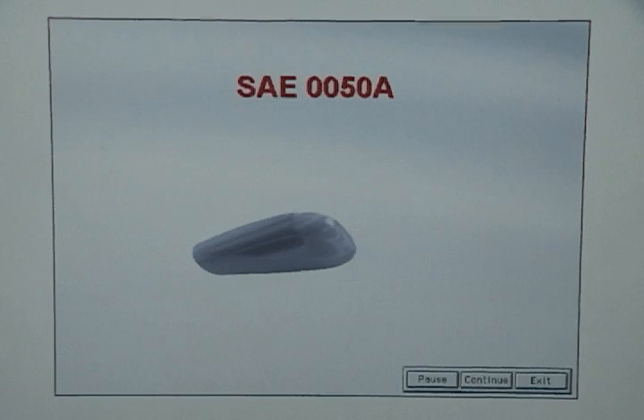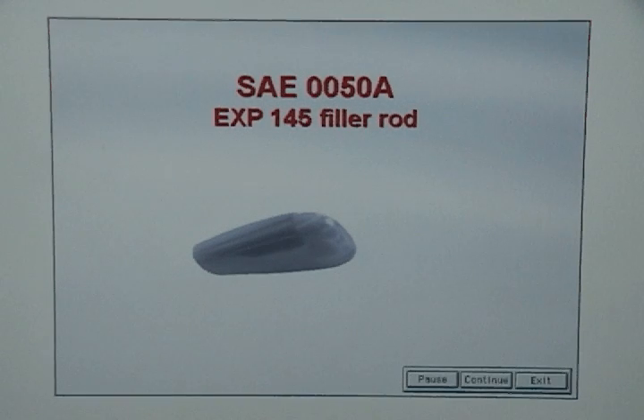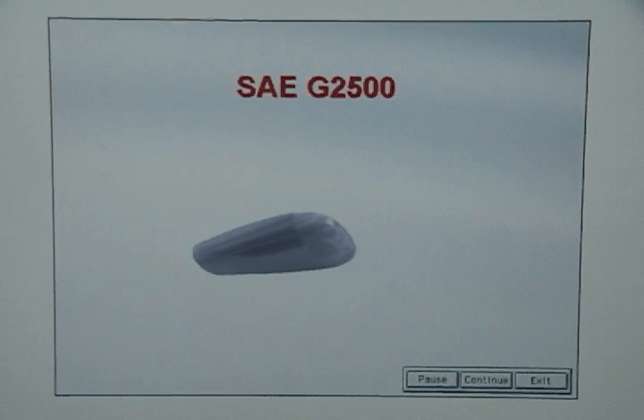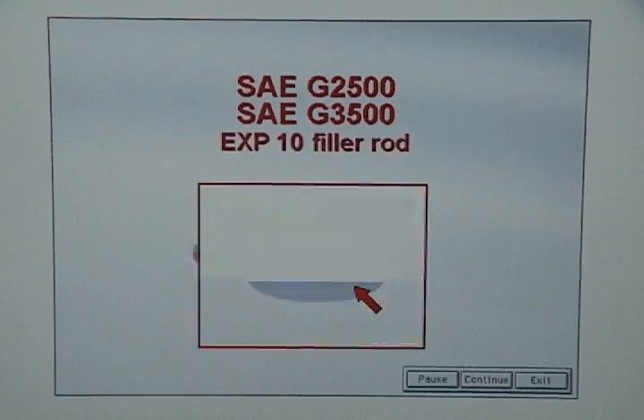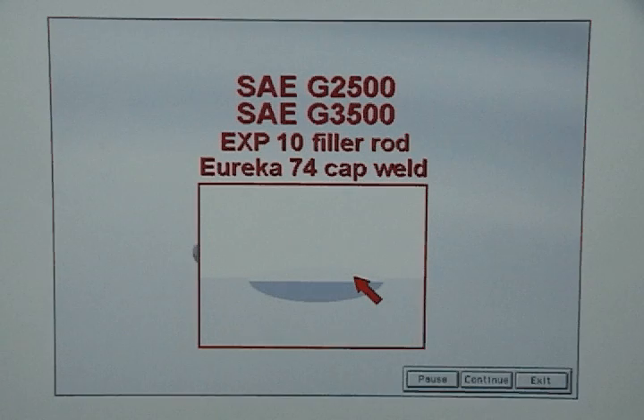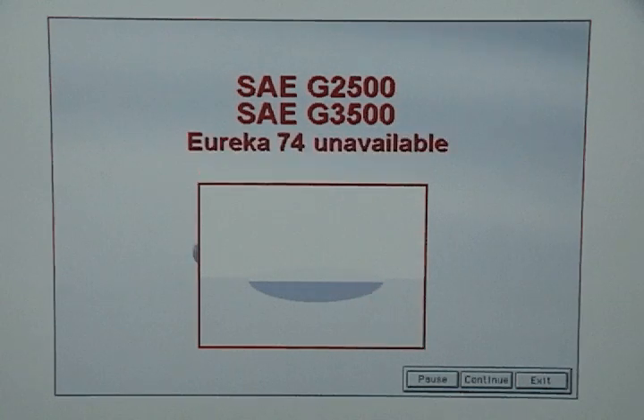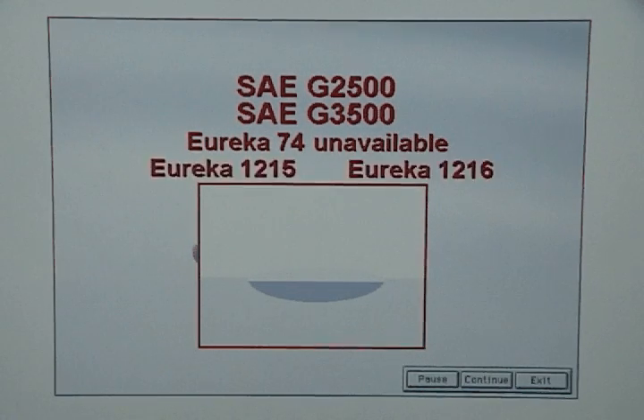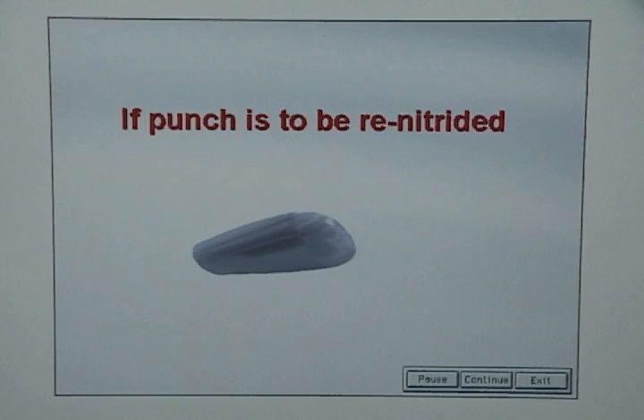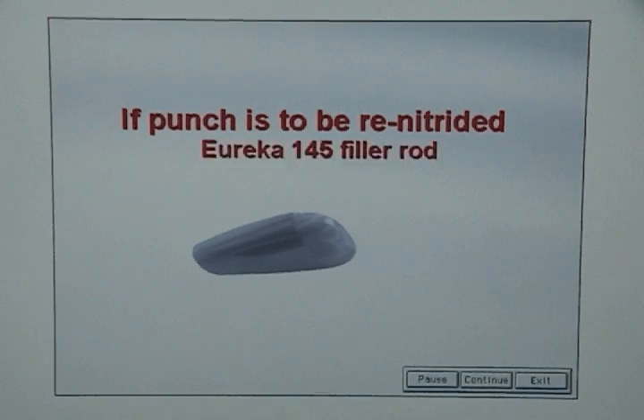If the punch is made of SAE 0050A metal, use an EXP 145 filler rod to weld up the repair area. If the punch is made of SAE G2500 or SAE G3500 metal, the welder will need to first build up the repair area using EXP 10 filler rod. After the repair area has been built up, place a cap weld over the built-up area using Eureka 74. If Eureka 74 is not available, Eureka 1215 or 1216 are acceptable substitutes. If the punch is to be renitrided, use Eureka 145 filler rod.